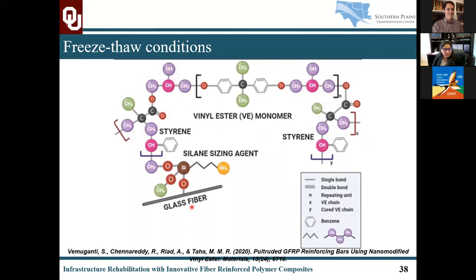In addition to the service load behavior as well as the different kinds of effects that the freeze-thaw has on FRP, it's also very important to understand how the bond changes between the resin and the glass fiber, how this freeze-thaw can affect the bond, and because bond is such an important parameter in this composite behavior, what kind of changes happen with freeze-thaw cycles, and is there any thermal incompatibility of these constituent materials, the vinyl ester monomers, the styrene component, the silane sizing agent of the glass fiber. Are there any incompatibilities due to the freeze-thaw and the moisture environment, what kind of damage do the FRP composites experience, and how consequently does this influence their tensile properties.